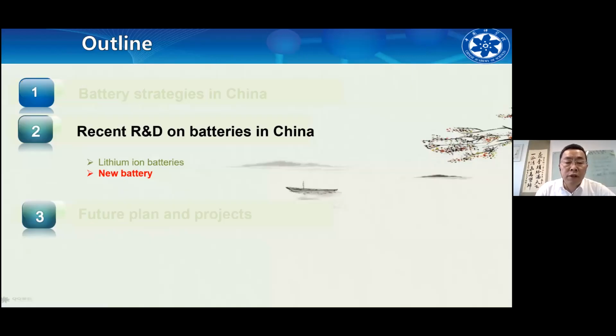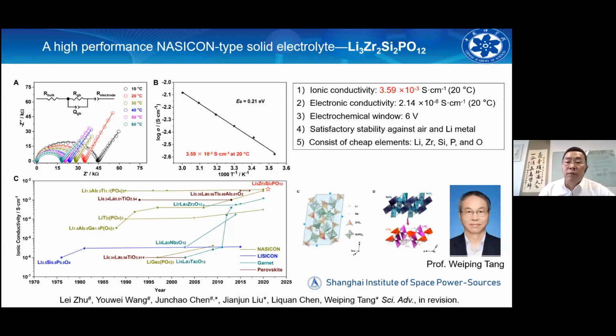And now I want to briefly introduce the new battery research. The material for the solid-state battery is a very hot topic in China. But for the oxide electrolyte, we need to find new oxide electrolyte materials. LLTO has been famous this year. Professor Tang has reported a new material, a so-called NASICON structure, lithium zirconium silicon phosphate. It has an ionic conductivity of 3.5 millisiemens per centimeter at 20 degrees C. This is the highest ionic conductivity at room temperature for an oxide electrolyte.